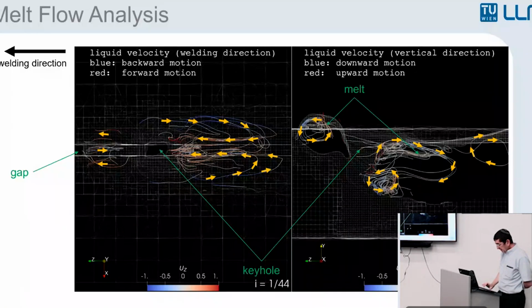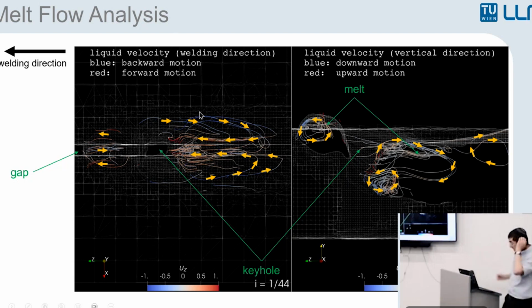This is another example. What you see on the left over here is a top view of 2 pieces of metal. From here to here is one, and from here to here is another, and there's a gap in between. In this particular case, this is a pipe with a 3 millimeter thickness, and when you try to weld the top seam, there's always a gap of a few hundred micron. So you can have filler material, but what we did here is designed a beam shape that acts like a shovel, and it takes material from the side and moves it to the center and fills the gap. Okay, this is really cool, and it works. So we actually are welding pipes like this where material comes from the side and is being pushed to the center to fill the gap.